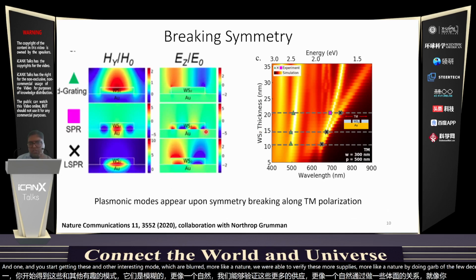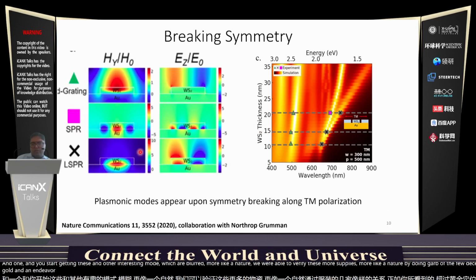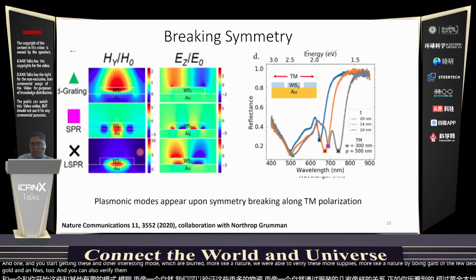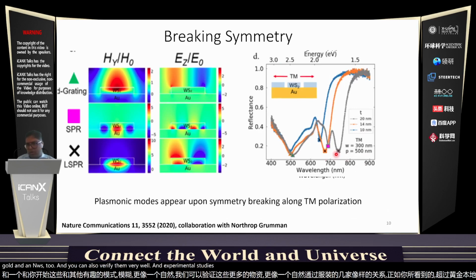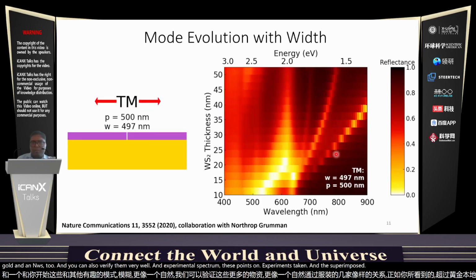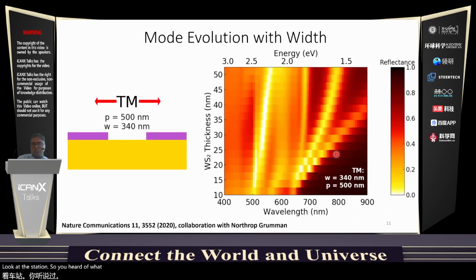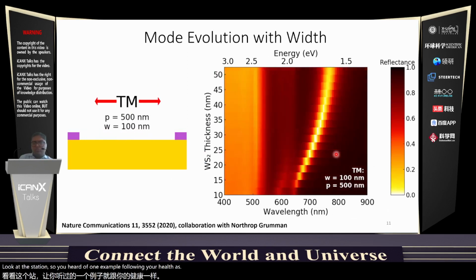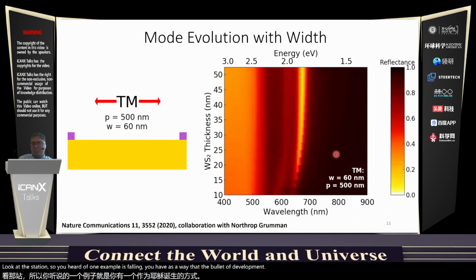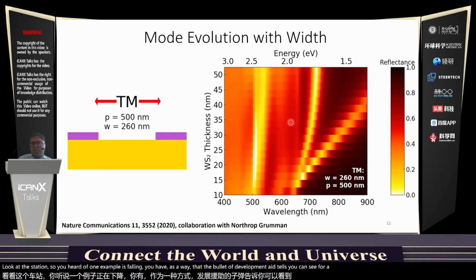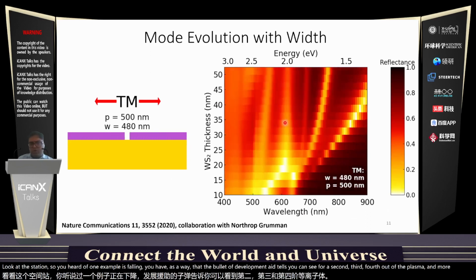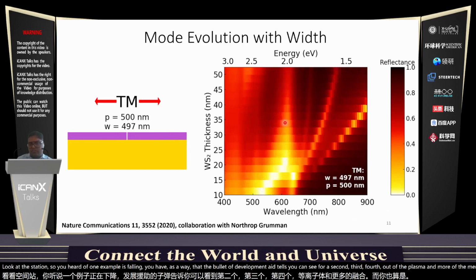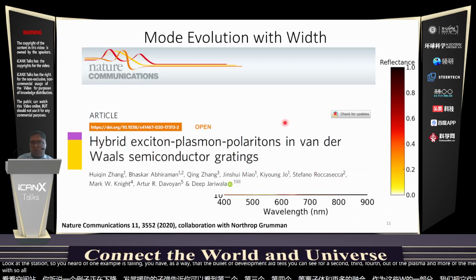As you can see, these modes are localized at the interface of gold and WS2, and you can also verify them very well in experimental spectra, with these points from experiments taken and then superimposed onto calculations. So here is one example showing how, as you vary the width of these resonators, you can see first, second, third, and fourth order plasmon modes emerging as you pattern these WS2 resonator widths. So all this was summarized in this nice paper that was published last year.